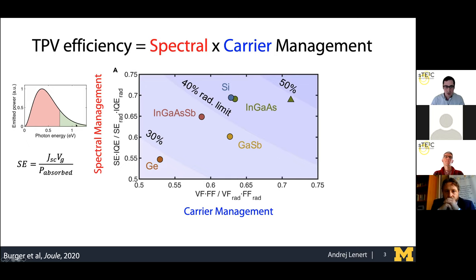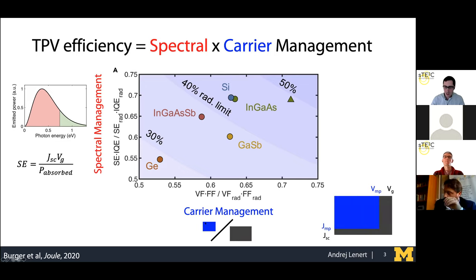So this, it could be a very broad distribution. And then carrier management is just the ratio of the blue box to the black box. And these are the current voltage characteristics of the device. So basically how much power is generated with respect to a product of the photocurrent and the band gap voltage. So that's what these two metrics show.